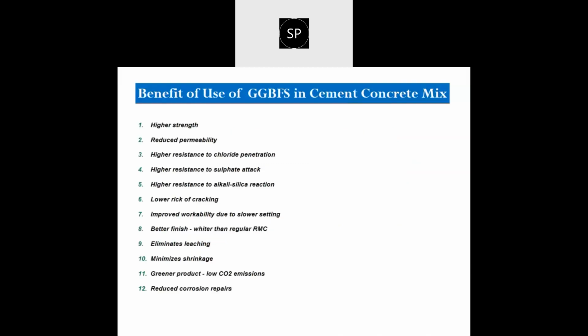So what is the benefit of using GGBFS in cement concrete mix? It offers high strength, and it reduces the permeability. Since it is a very fine powder, it basically fills all the permeable voids inside the concrete mix and reduces the permeability of the concrete mix significantly. It has high resistance to chloride penetration, since the Portland slag cement shows very good resistance to chloride and sulfate attack. You can use Portland slag cement, or you can directly use GGBFS along with the OPC, in order to construct a durable concrete structure in a marine environment. Besides that, this sort of cement shows high resistance to alkali silica reaction.